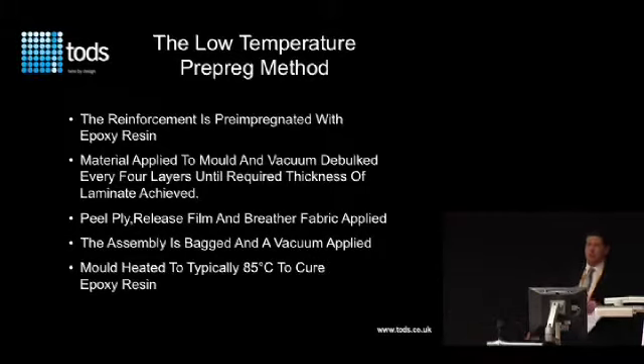So with low temperature prepreg, it is what it says. It is a pre-impregnated material that's applied to a mould. You usually vacuum debulk the first layer and then subsequently every 4 layers. You then apply the normal peel ply, release film, etc. Apply a vacuum and cure it typically at 85 degrees.